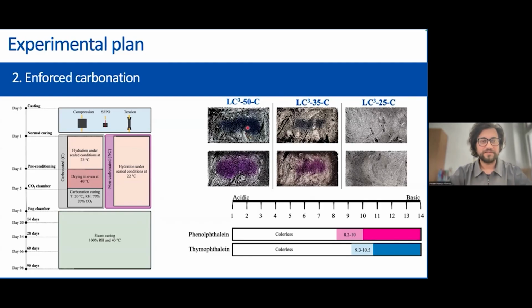So the first thing you notice is that LC350 and LC335 were not fully carbonated. Because the Portland cement content is high in these matrices, they are naturally denser materials. So the carbonation condition that we applied for all three means we need harsher or somewhat stronger conditions for these matrices to fully carbonate. While LC325 has very low clinker content and its microstructure is not so dense, CO2 could easily enter and carbonate it fully. Looking at the color, you see the shell around this non-carbonated core is almost colorless. That means the pH is below 8.2, even in these high alkalinity matrices after carbonation. While LC325, which is fully carbonated, shows colorless. That means the pH in all the system where you don't see color is below 8 or 8.2.